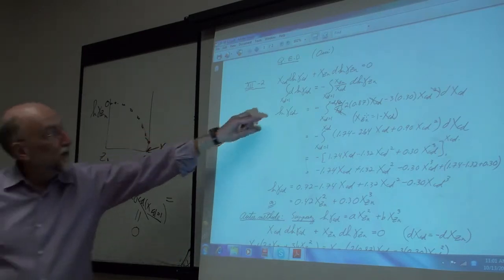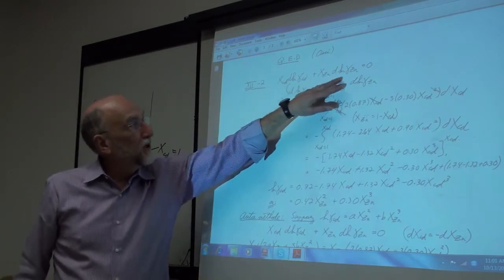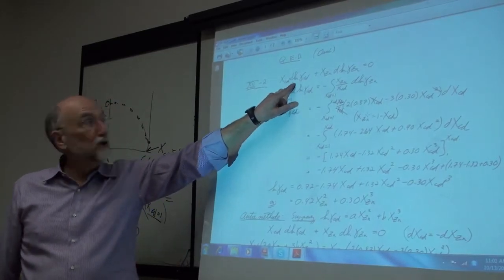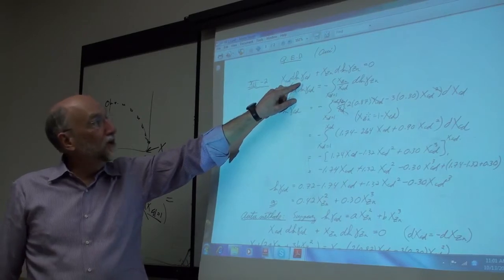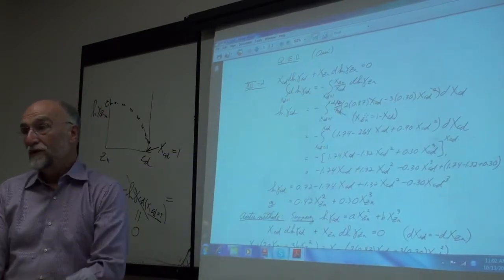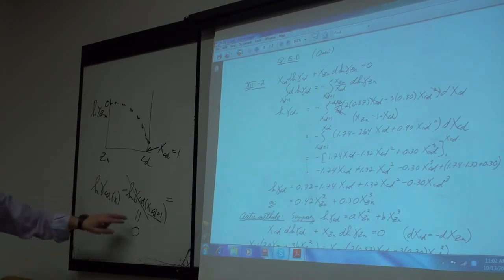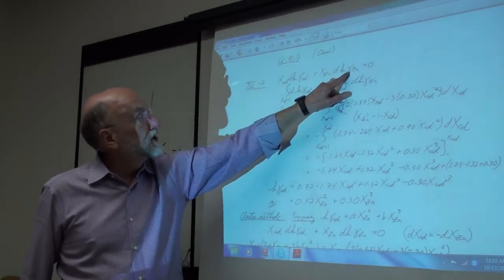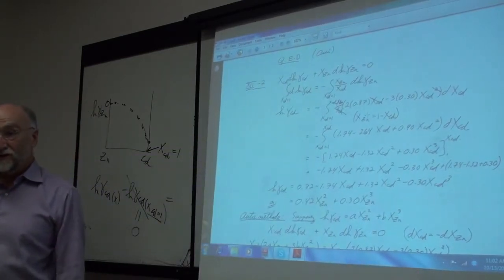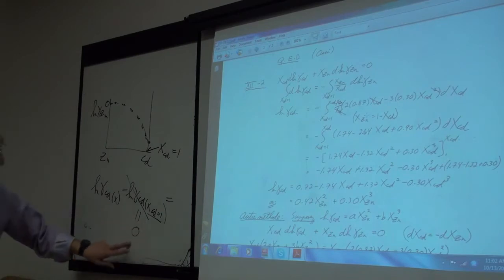Okay, so I've taken my lower limit of integration. When you're doing an integration, remember, this is a differential equation. I have an expression for log gamma zinc, which I'm given. I'm trying from the differential equation to obtain the corresponding expression for log gamma cadmium. In a differential equation, you can always calculate this other function within a constant of integration. There's always going to be a constant of integration when you solve a differential equation by integration. In this case, the constant of integration is log gamma cadmium at the lower limit, where we happen to know it. So you need the expression for log gamma zinc as a function of composition, and you need one value of log gamma cadmium at some point in order to obtain the constant of integration. So we pick a point where we know the activity coefficient of cadmium, and this is our constant of integration.